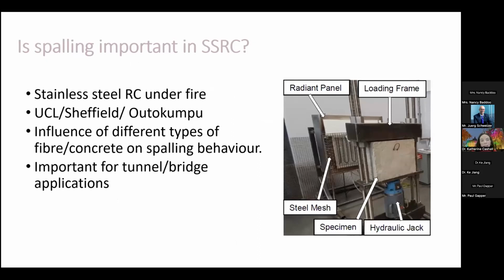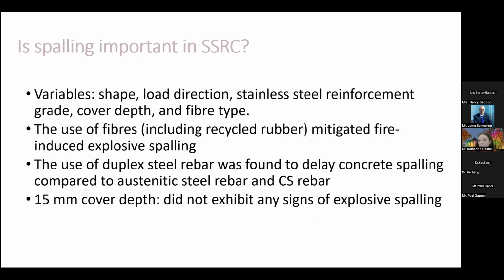We've got some tests underway at the moment, together with another university in the UK, the University of Sheffield, looking again at whether or not the spalling behavior in concrete is different for stainless steel rebar compared with carbon steel reinforced concrete members. And the initial results are showing us that it's not that different. So there's no real issue. And just like with regular concrete, incorporating fibers into the mix can be very influential and positive for delaying spalling. Indeed, even for only 15 millimeters of cover, we still didn't have any signs of explosive spalling. So that was a very positive outcome from that study.